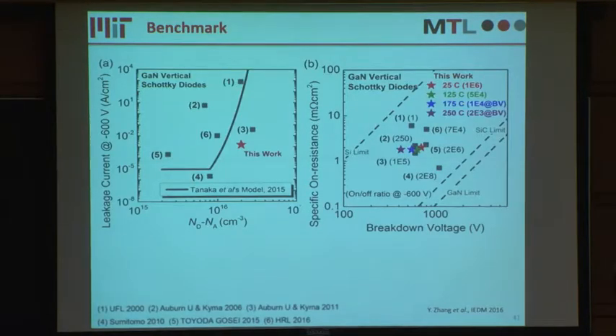So then we need to benchmark our performance with other vertical gallium nitride Schottky diodes. For vertical gallium nitride Schottky barrier diodes, people have found that the leakage current is very sensitive to the net donor concentration in the drift region.